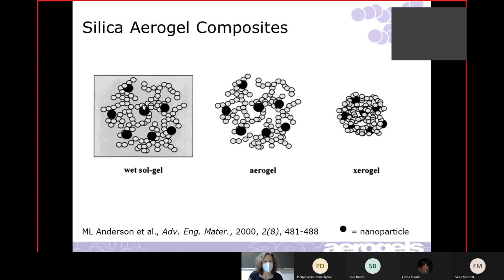If you can get the solvent out of the pores without pore collapse, these are then going to be accessible to do interesting sorts of applications, right? It could be a catalysis application. It could be an energy or sensing related application. They will still be accessible to gas phase things. Under drying, under ambient conditions, it's going to collapse, and that may make whatever we've just put in fairly inaccessible to anything else. So the advantage of the aerogel here is the porosity.